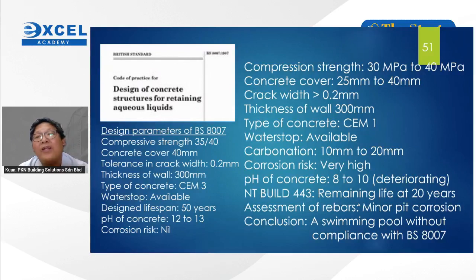Okay, and this is what we found out after all the tests. Compression strength is between 30 to 40 MPa. Concrete cover between 25 to 40. Crack width more than 0.2. Some of them are 0.3, 0.4, 0.5. Thickness of the wall 300 mm. Okay, but the type of concrete is CEM 1. So the type of concrete has very big implication when it comes to the crack control as well as the density of the concrete. Water stop, there are water stop there.